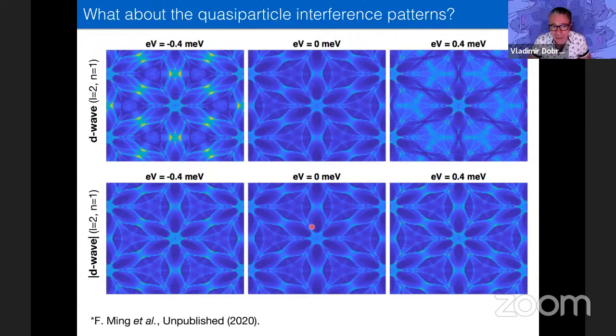Now I wonder. If I understand correctly, the QPI procedure is basically you calculate the full scattering from one impurity, and you assume that the cross terms are negligible because these are weak impurities or dilute impurities or something like that, right? Dilute, yeah, that's the assumption. So if you can solve the same one impurity problem, but in the presence of strong correlations, that would tell you something. It seems to me that the results you've shown, which is obviously the first thing that you do, is to just try a non-interacting tight binding model or band structure. Then you put one impurity, you do the Friedel oscillations, and you get this pattern. But let's imagine that if you have strong correlations, this one impurity scattering is dramatically modified now, or there is this phenomenon of healing.